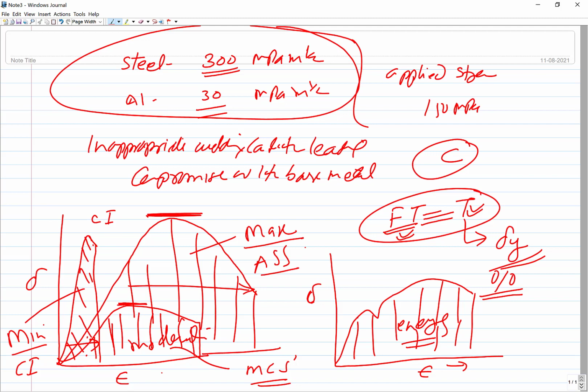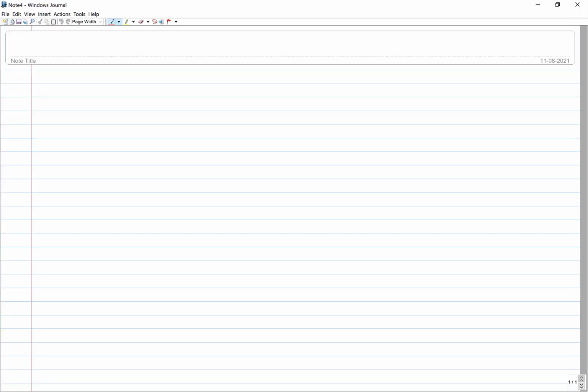So if you see here, the yield strength, the tensile strength and the percentage elongation both contribute towards the toughness. Since toughness and fracture toughness go hand in hand, the greater the yield strength and the greater the ductility, the higher the fracture toughness also. So those metals which show good ductility in combination with good yield strength certainly show high fracture toughness.